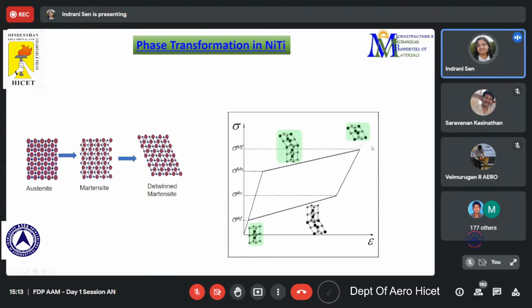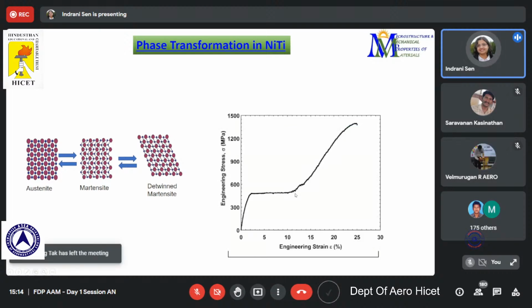Now the beauty is that up to this level, if we have applied the stress and it has attained a certain amount of strain, and now if we simply unload it, it comes back to the initial starting phase, that is the austenite phase, and this entire amount of strain gets recovered. So that makes it an interesting system. This is how the stress strain curve looks like.